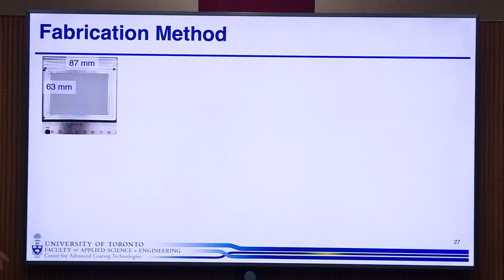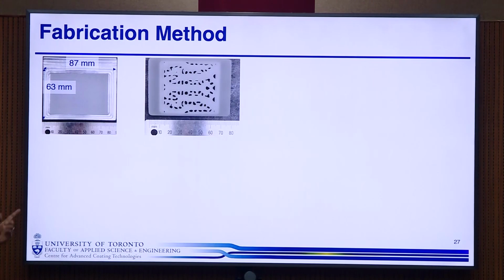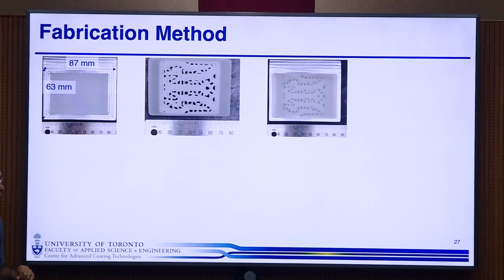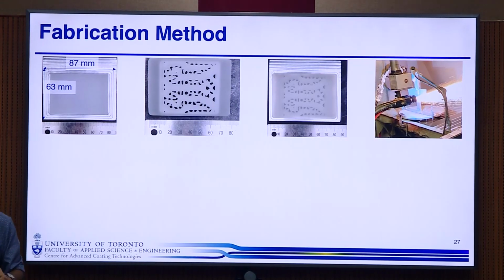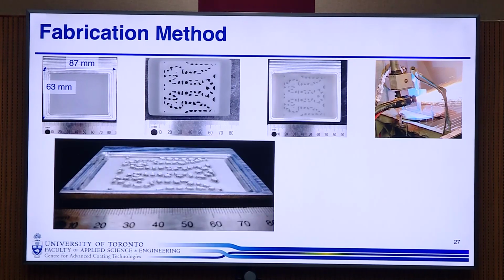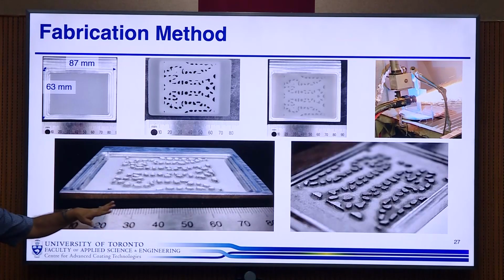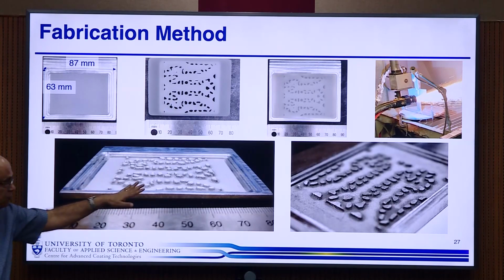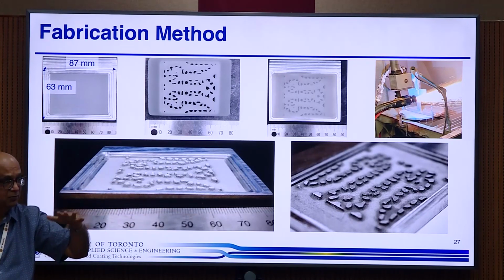Okay, showing the fabrication. We take a metal plate, and we put about a 3 millimeter deep cavity inside it. We 3D print a mask out of polymer. We fit this inside. We spray the metal on that. And then you remove the mask, and this is what you are left with. These are the structures. And then we take it and grind it down, so you've got a uniform height, in this case 0.75 millimeters.